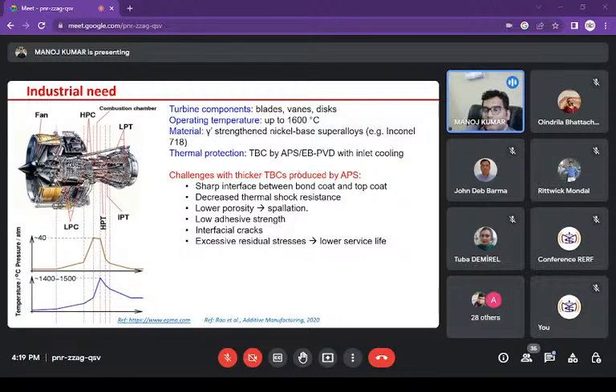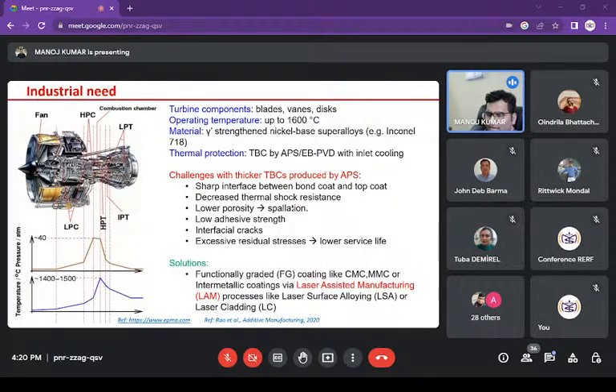Now these TBCs have been in use for quite a long time, but there are still some problems associated with them, like a sharp interface. When you deposit a ceramic coating over the metal, there is an intrinsic difference between the characteristics of the metallic substrate and the ceramic top coat. They do not match in terms of properties, so there is a sharp interface between the metal and the ceramic coat. This always leads to development of stresses at the interface and adherence issues, and that leads to failure of the coating. So now what can be the solution?